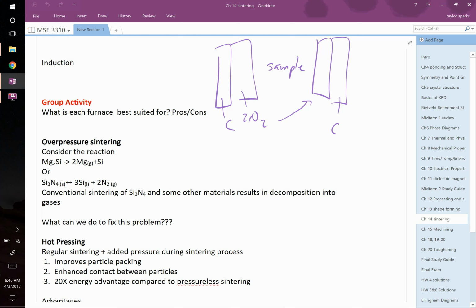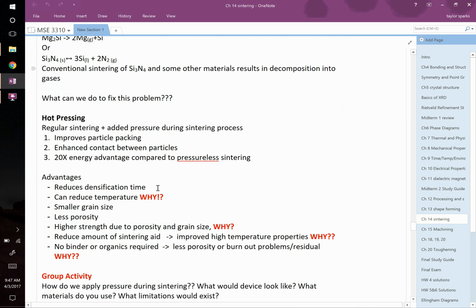We've described lots of different shape forming processes and sintering. Hot pressing is sort of a mixture of both shape forming and sintering, right? You do them both together simultaneously, ideally. So it's just like regular sintering in that heat, time and temperature are working. But now, in addition to time and temperature, you're providing a way larger force than just capillary forces, right? The pressure you're adding can greatly enhance the densification effect. It improves particle packing because once you heat things up and apply pressure, they're able to pack together better. It also gives better contact between particles.